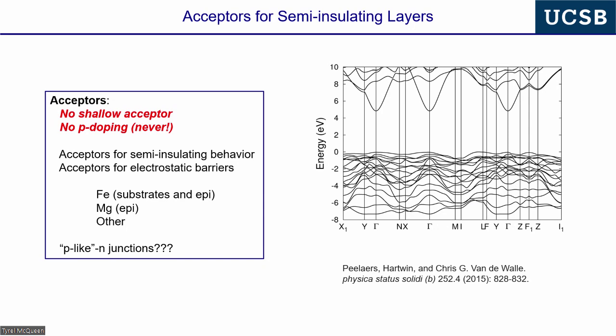So there's no evidence in gallium oxide that we have a shallow acceptor. There's no evidence of a shallow acceptor, and that's a necessity really to have p-type doping. And the valence bands are extremely flat. So if holes form, you can always form holes in any semiconductor by just optically exciting with above band gap light. You'll create holes. But those holes in gallium oxide will immediately localize with the lattice, forming a strong polaron. So they're very heavy as free carriers, then they become that much heavier when they form polarons.